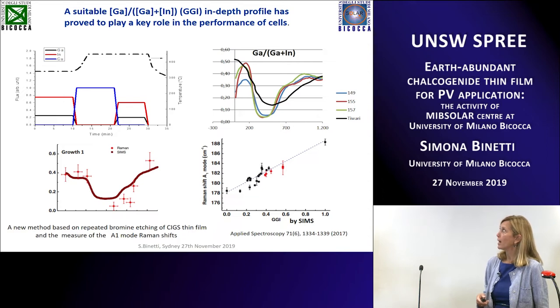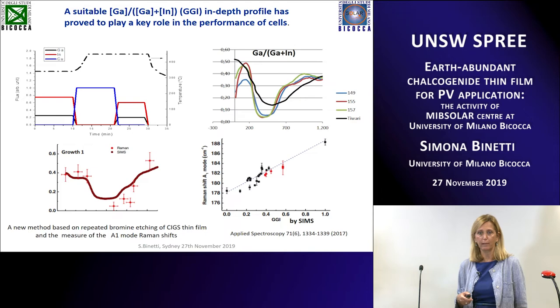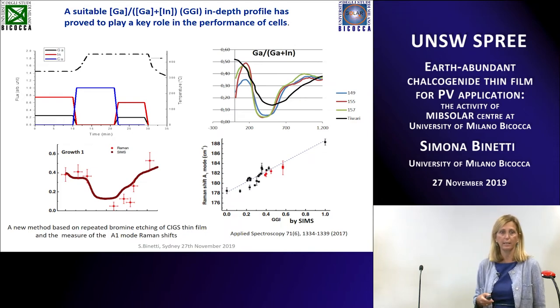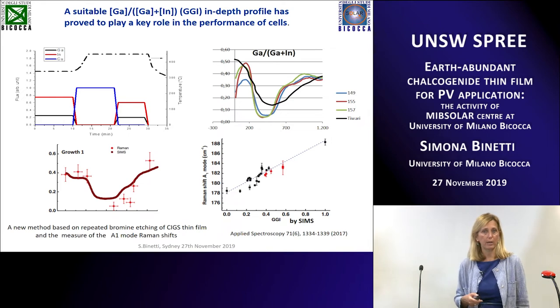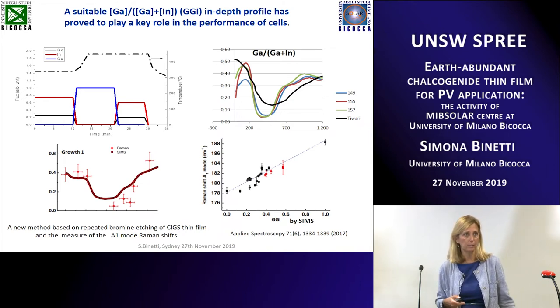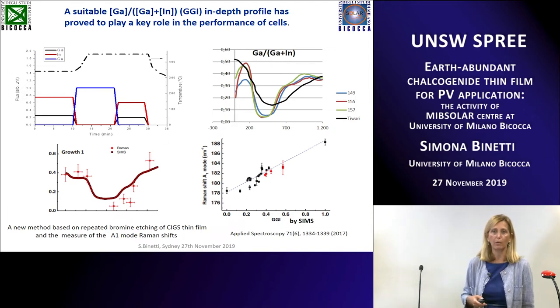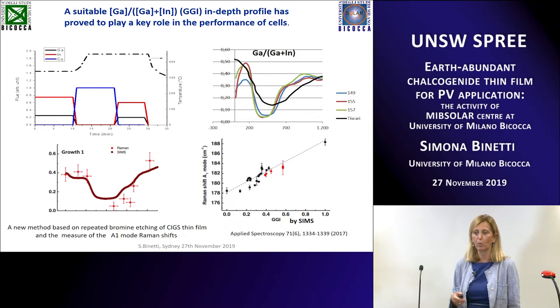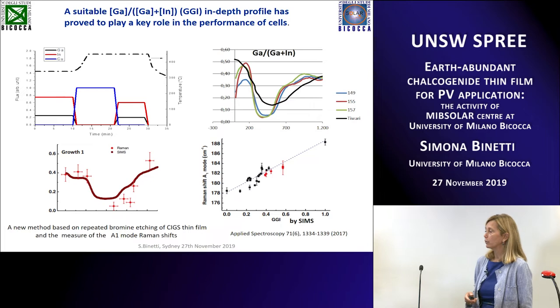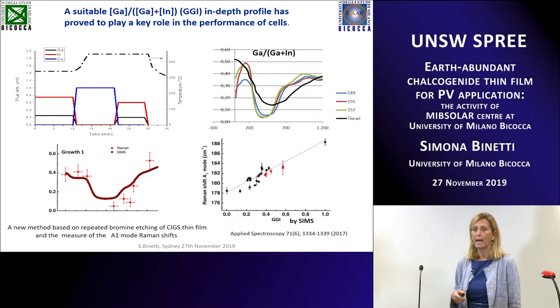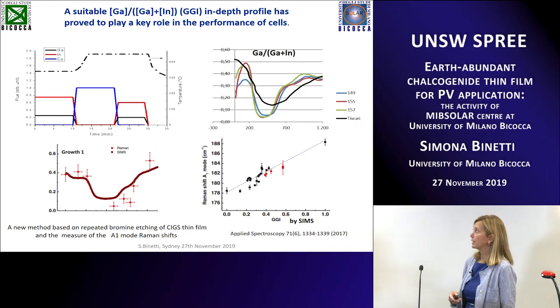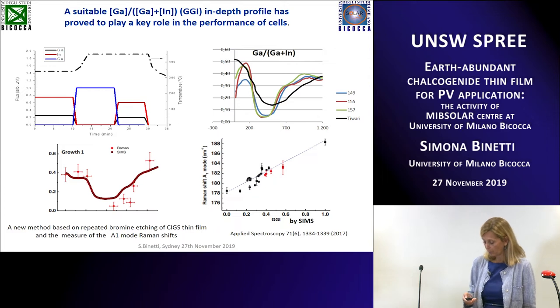Considering that this type of GGI profile plays a key role in getting high efficiencies, in order to check this profile it is necessary to perform secondary ion mass spectroscopy. That is quite an expensive technique that is not available in every lab. For instance, in Italy we have just two equipments, in the north of Italy, quite far from Milano. And so we developed a new system based on repeated bromine etching on CIGS thin film in order to make a correlation between the profile and the GGI ratio based on Raman spectroscopy, studying the Raman shift versus the GGI concentration, obtaining a good agreement with